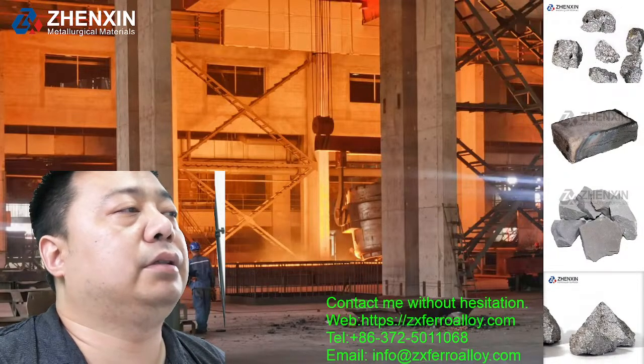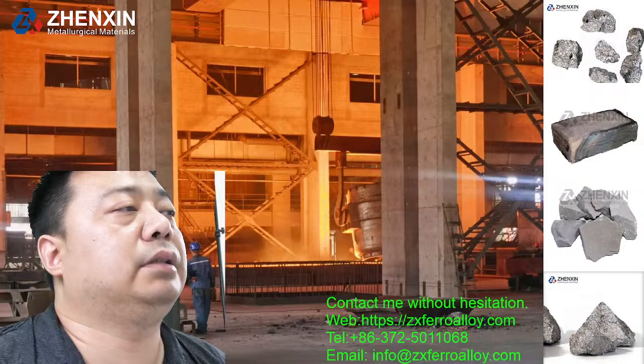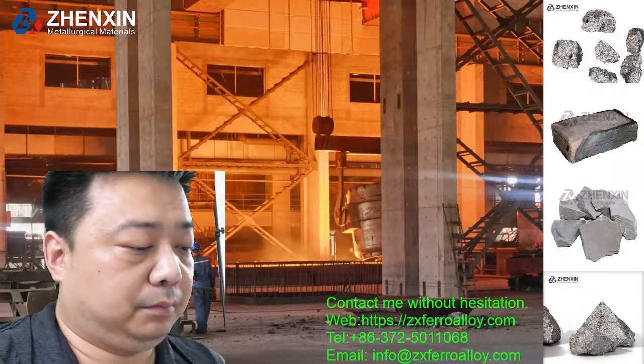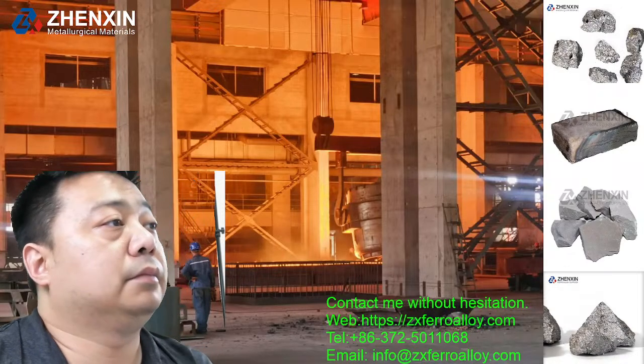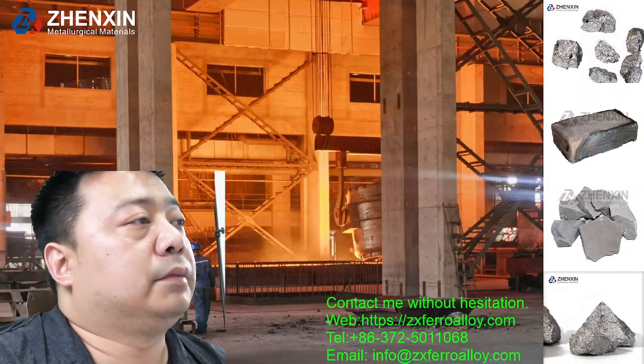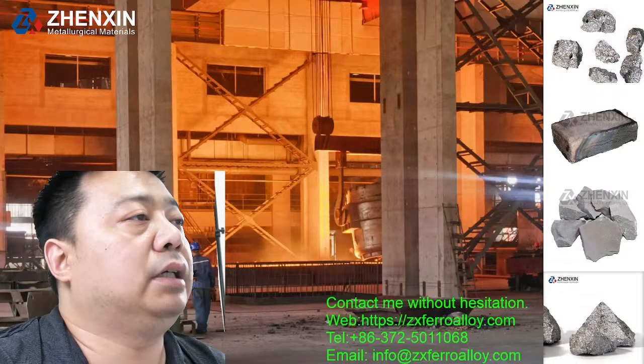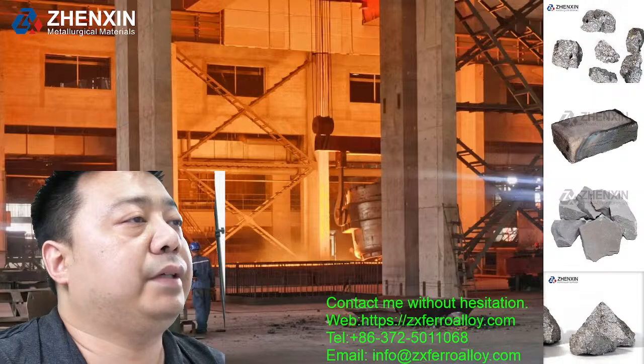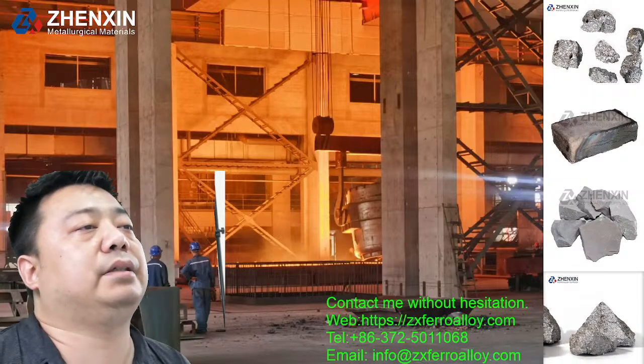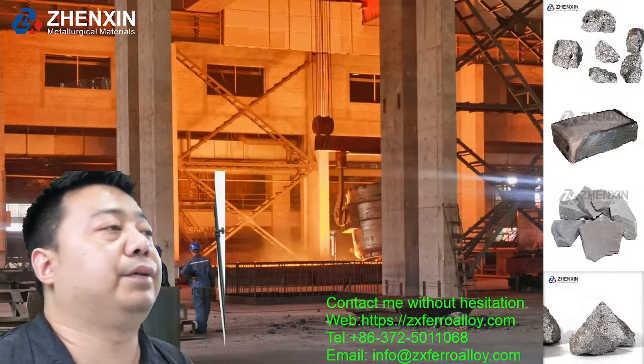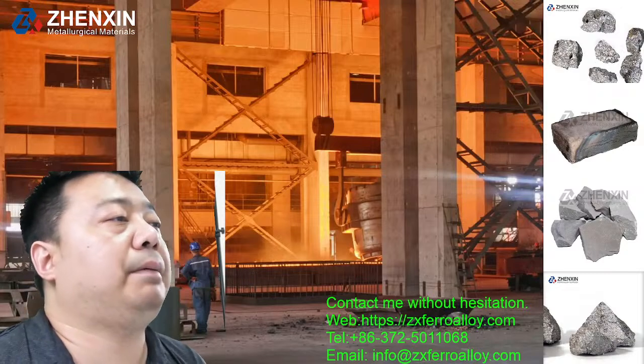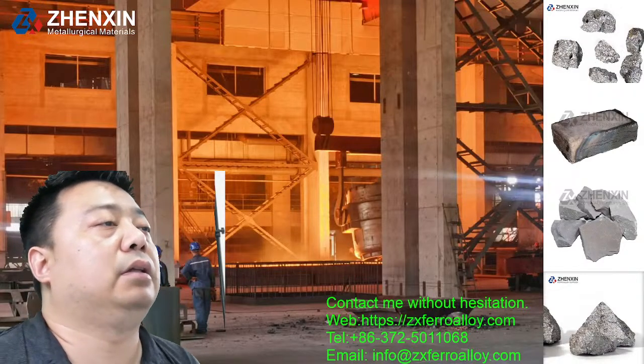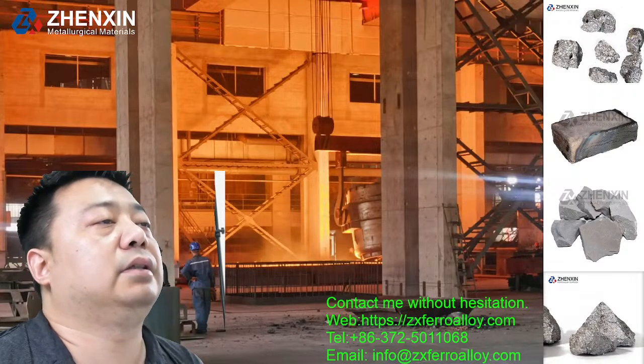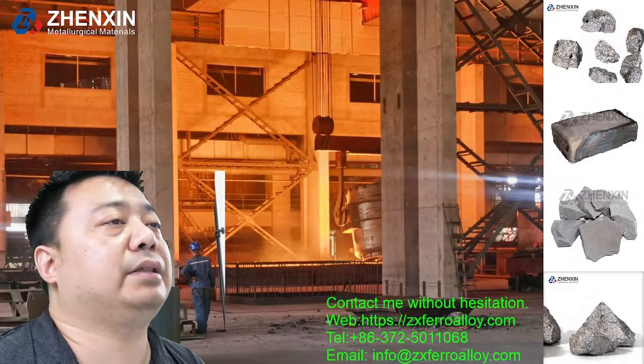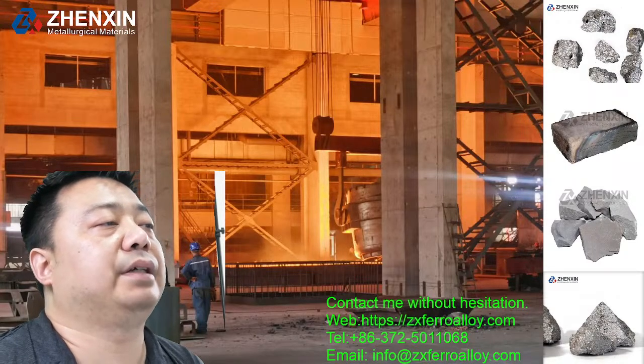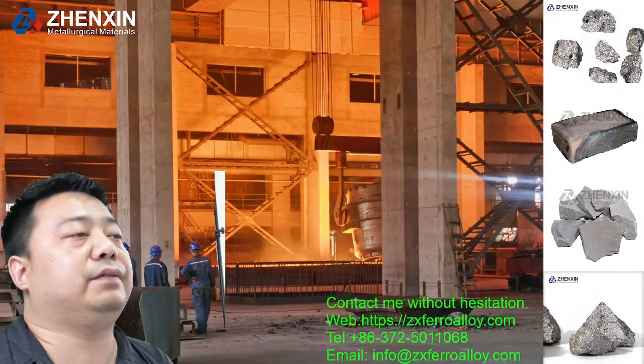Thus failing to achieve the desired effect. On the other hand, the gasification of calcium particles in the molten steel will form a larger vapor pressure, which will cause the molten steel to splash violently, which directly affects the service life of the electric furnace and the smelting furnace.